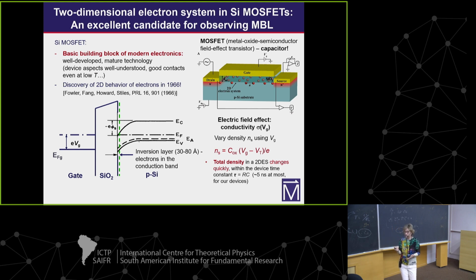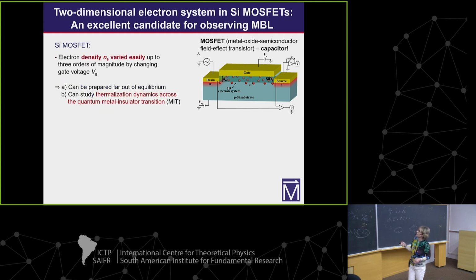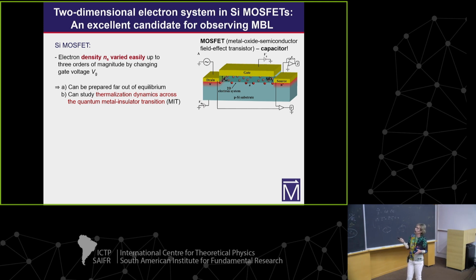So for our purposes, this is an instantaneous process. This is a good system to study because we can change the carrier density easily over 3 orders of magnitude. It means we can prepare the system far out of equilibrium easily simply by changing the gate voltage. We can also study thermalization for many different carrier densities, in particular across the quantum metal insulator transition.